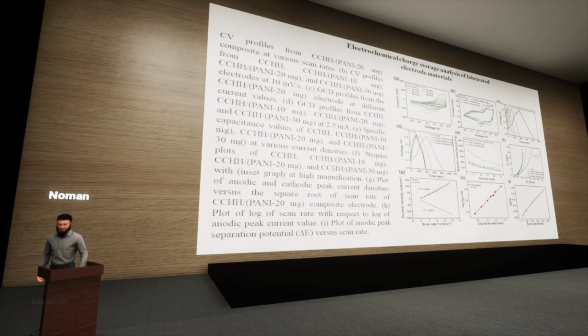This is the cyclic galvanostatic charge discharge of the material. We can show the maximum results, and this is the comparison of all the samples, which shows that the discharge time for 20 milligram addition of polyaniline is maximum, which is in good comparison with the cyclic voltammetry. And this is the specific capacitance with respect to changing the applied current.